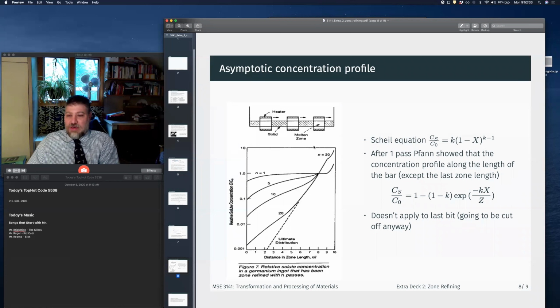Could this be paired with an extruder to get 5N pure right out of the gate? So the question though is, what are you feeding into the extruder? Essentially we have a bar. Generally for metals this would be a casting, a bar-shaped directionally solidified casting. Because if you do directional solidification, you get solute rejection, directional freezing, and so you can get a relatively high purity casting. And then the zone refining is used to clean up.